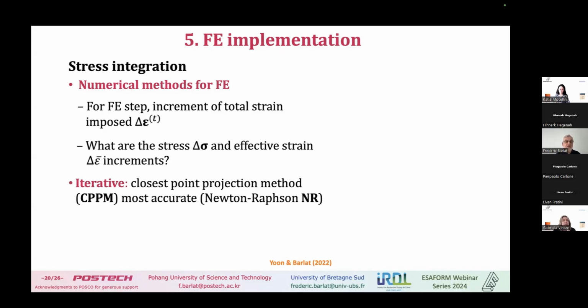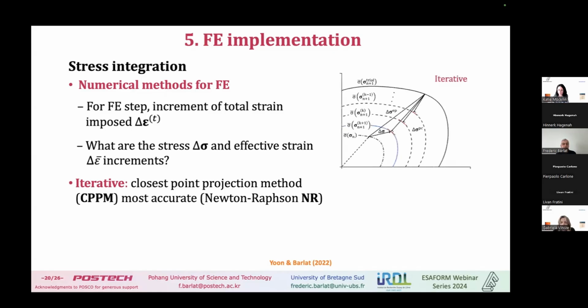So the most used, most powerful method is the closest point projection method, or CPPM. It's the most accurate, and basically it's Newton-Raphson. But this is a method that takes some time, because we first do a prediction using an increment that is totally elastic, and then come back iteratively to the solution. And this takes some time. And the reason we wanted to have something simpler and faster, maybe not as general as this method, which can be applied in many problems.